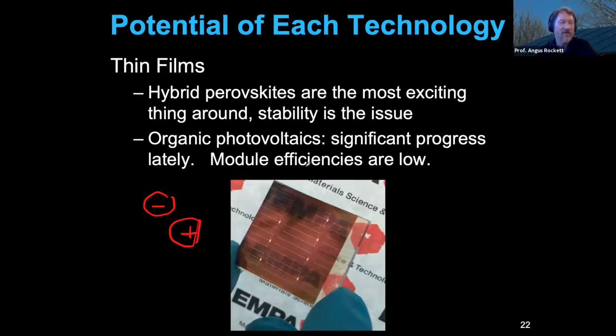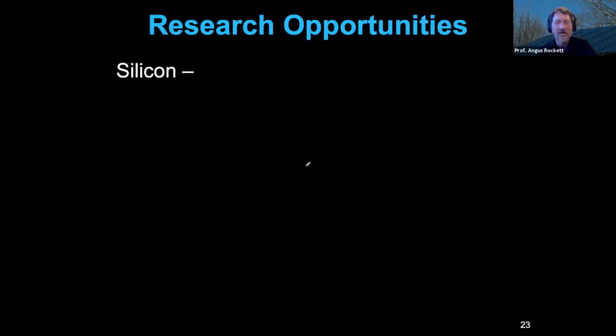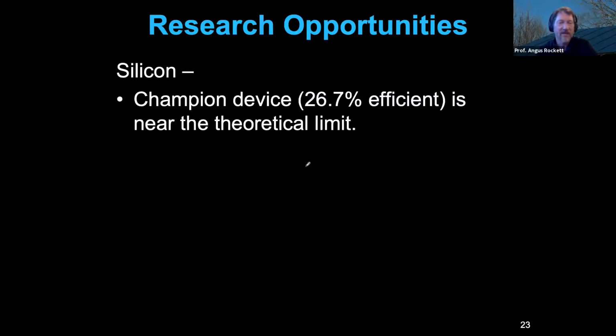I'm going to mention some research opportunities now and a few things that are going on with each of these. So one of the problems for silicon is that the champion device, the best small device that's been made with silicon, is 26.7% efficient. And that's very close to the theoretical limit. So there's real questions about whether you can improve silicon in a champion device at this point. People have been saying that for a while, and they've still managed to make improvements, but this is getting very close to the real theoretical limit. So what can we do?